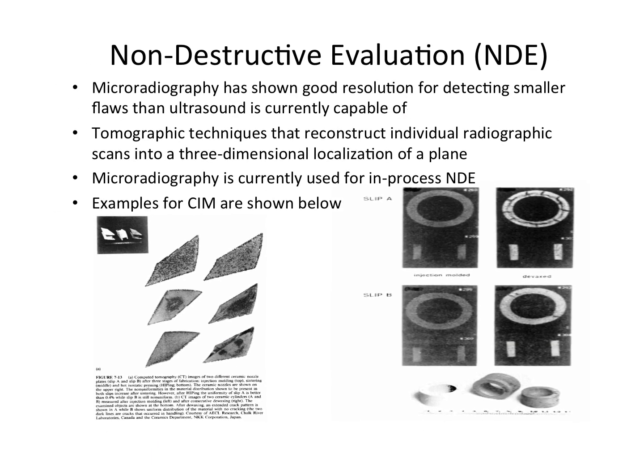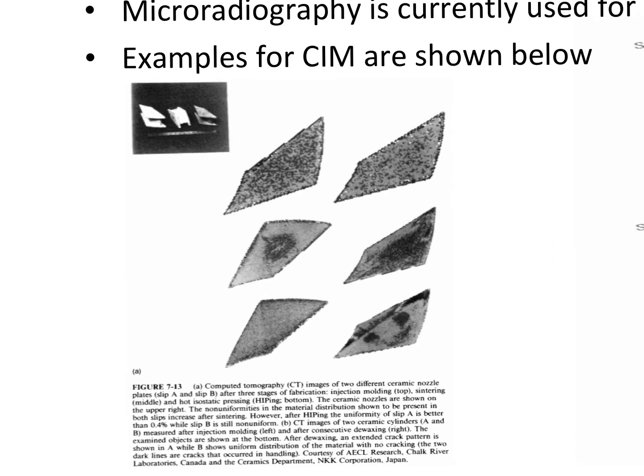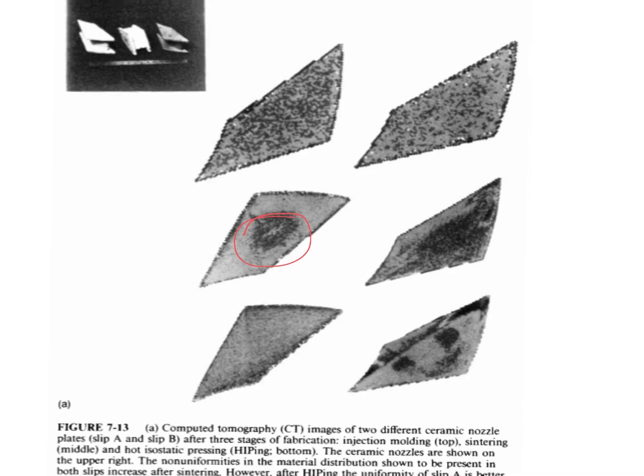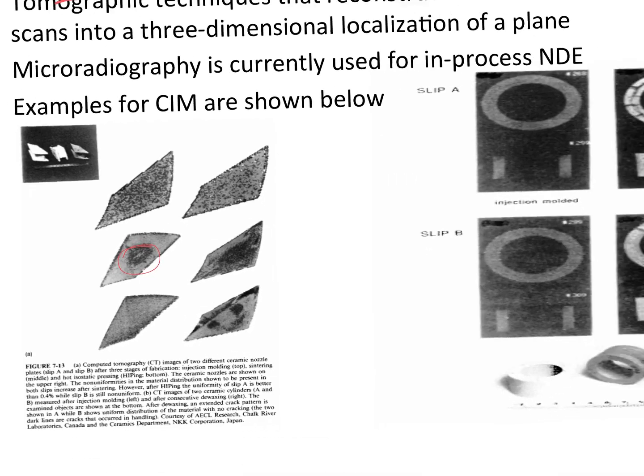We also use X-ray CT, and X-ray CT is wonderful stuff. Good resolution for detecting smaller flaws than ultrasound is currently capable of. It's also non-destructive. It doesn't shatter the part like MOR does. Modulus of rupture, you have to break the part. But with X-ray CT, and these are some examples of silicon nitride airfoils, you can scan these things internally and get an idea of the flaws, how many of them there are. There's a concentration in the middle of this one, for example, that might be of concern. And how that relates to the process, it's very complicated, but that allows you to look at these things.